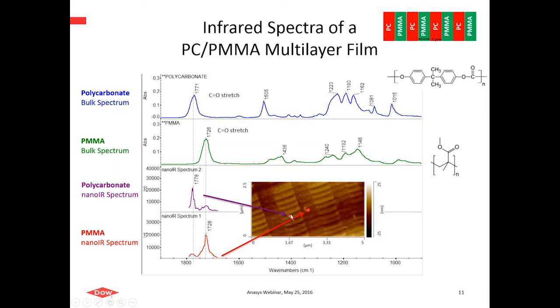If we put the AFM probe down on either alternate layers and collect a spectrum using the AFM-IR, in one case on one layer now we see a strong absorption that's coincident with that for the polycarbonate, 1778 wave numbers, and then in the adjacent layer we see a strong absorption due to the carbonyl from the neighboring PMMA. So clearly we can set the probe down and identify the alternate layers and which is which.